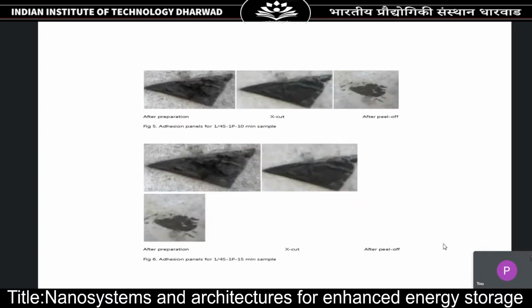We have done some adhesion tests which are based on ASTM. So these are called the cross-hatch method. So we have taken the sample after preparation, we have done the cross-hatch, then we have done a peel off. So this is done for two types of samples. So you can see that some of the samples retain a significant amount of the coating even after peel off. So that shows a very good adhesion of the coating to the glass.